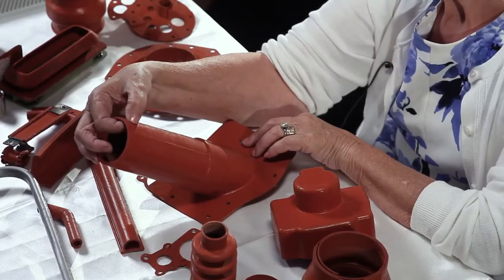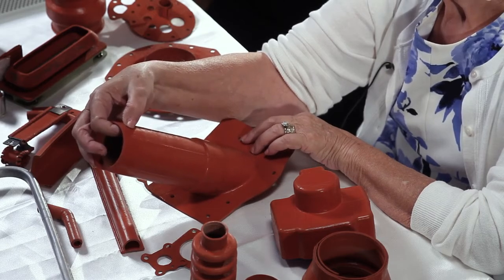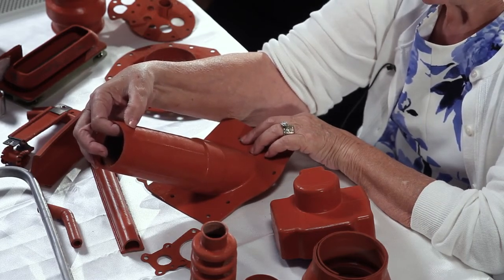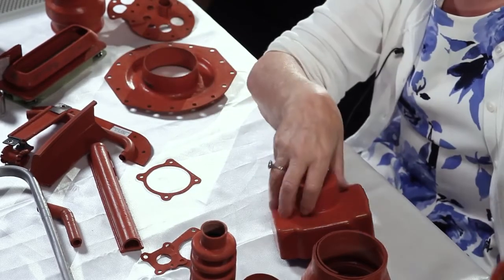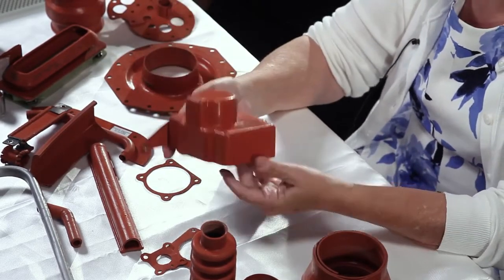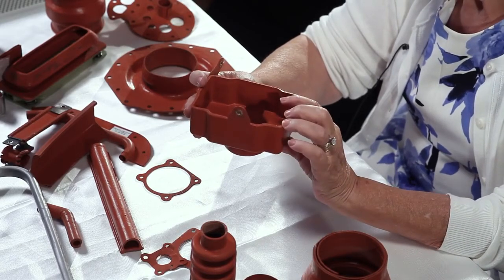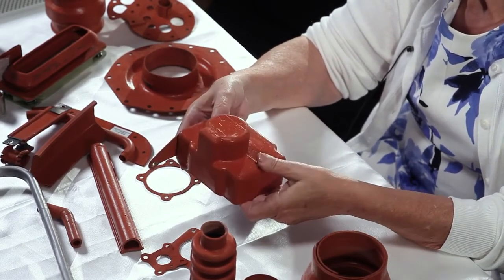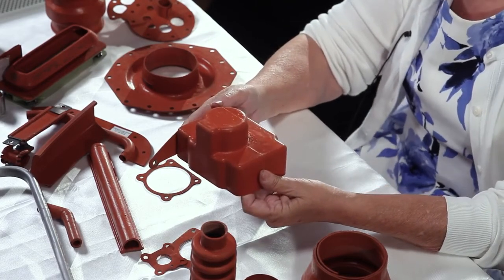Fiberfrax is paper. It doesn't bond to anything. It is miserable to work with. But because we encapsulate it, it works. Over this 90 thousandths, we get a 600-degree temperature delta. This part is still flying, and we've never had a failure or a complaint. That morphed into this part, which we make for UTC. It's a valve cover, and it is only 50 thousandths thick using the same technology. This was developed for a fire test where the outside burn is 2,000 degrees and the inside had to stay below 300. Over a 15-minute burn, the ID temperature never went over 280.